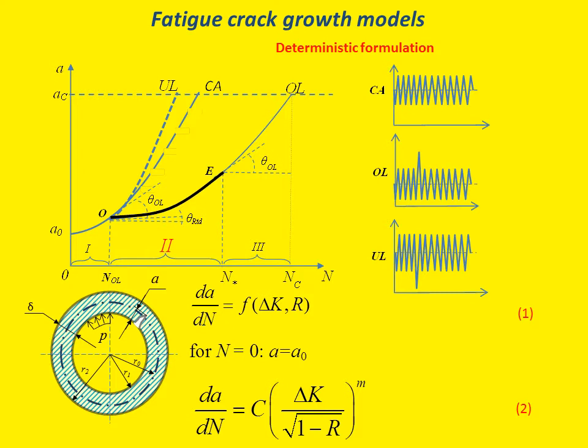Many mechanisms were considered to be involved in crack propagation after application of an overload, such as residual stress effect, crack closure effect, crack tip blunting, and strain hardening. However, there is still no general consensus on the relative importance of those mechanisms. The presence of such overload cycles predetermines a much more complex kinetics of fatigue cracks.